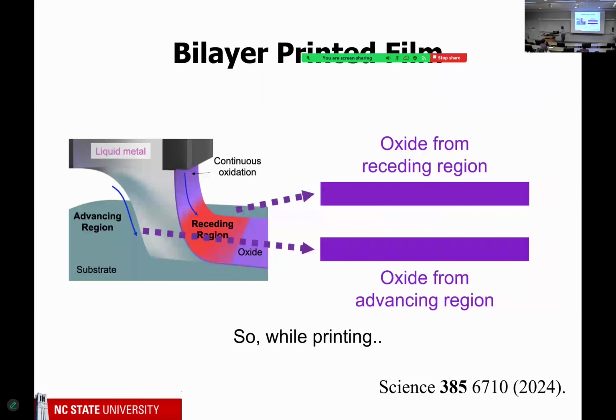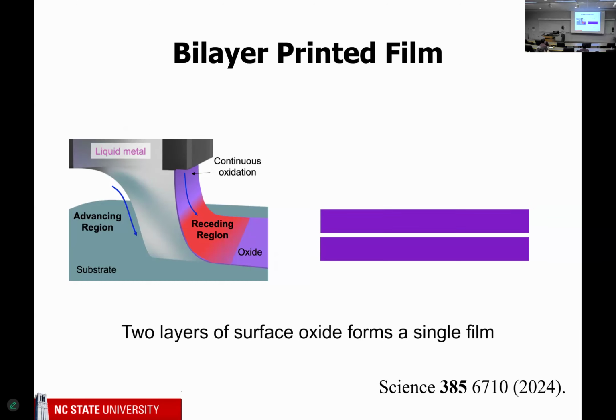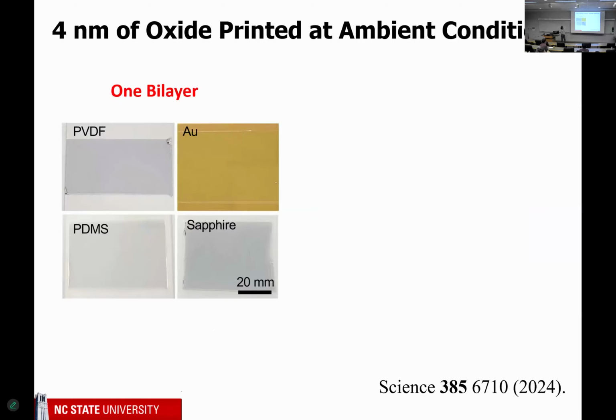Okay, so I mentioned before that you have oxide on the leading edge and the trailing edge, and they collapse on each other, so you actually end up getting a bilayer. That bilayer is about 4 nanometers thick, which we've measured in a number of different ways. This is what it looks like. We've printed on all sorts of different substrates, PDMS, sapphire, which is kind of like an oxide, gold, different polymers. And you'll notice, I'm going to come back to this, but you notice this kind of grayish color. That turns out to be important. It's transparent, but it's gray.